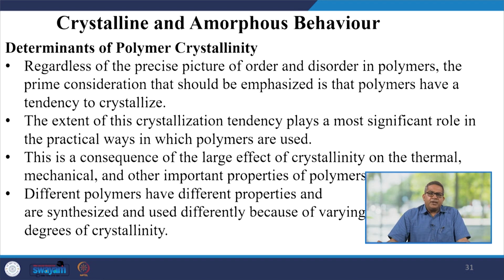Now, how can we determine polymer crystallinity? Regardless of the precise picture of order and disorder in polymers, the prime consideration that should be emphasized is that polymers have a tendency to crystallize. The extent of this crystallization tendency plays a most significant role in the practical way in which polymers are used, as a consequence of the large effect of crystallinity on thermal, mechanical and other important properties of polymers. Different polymers have different properties, and they are synthesized and used differently because of the varying degree of crystallinity and thereby varying degree of processing.